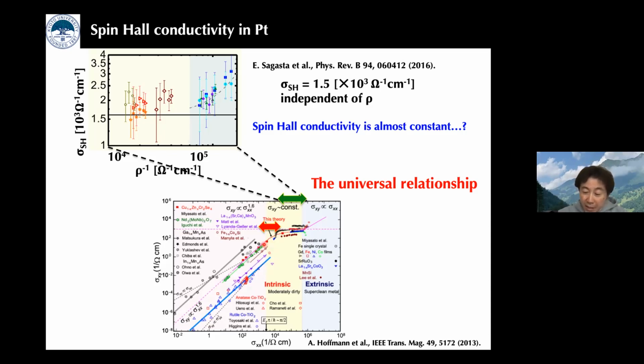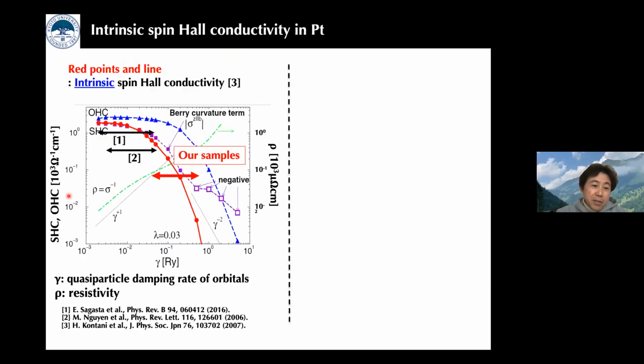And in the highly resistive regime, spin Hall conductivity changes largely as a function of the conductivity. This result is the theoretical calculation carried out by Kontani and co-workers. And as you see, the Berry curvature term becomes dominant in the highly resistive regime, and thanks to this contribution, spin Hall conductivity can be largely modulated as a function of conductivity.